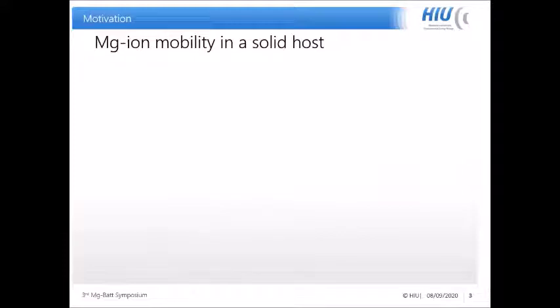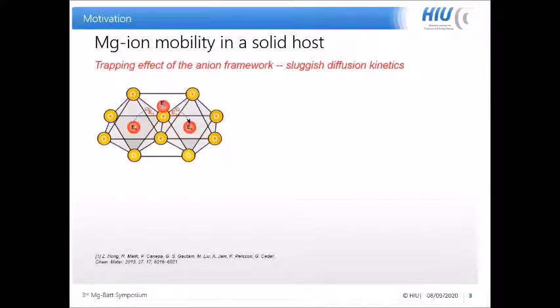So, as presented previously, there are a lot of issues related to magnesium ion mobility, and the reason is simple: we have a bivalent shuttling ion, the magnesium ion. The fact is that if we want to make use of the high charge density to get a high energy density, we also suffer from the strong interaction between the shuttling ion and the cathode. This is particularly prominent in the case of oxides, where we have this trapping effect of the anion framework, and this also leads to very sluggish diffusion kinetics.